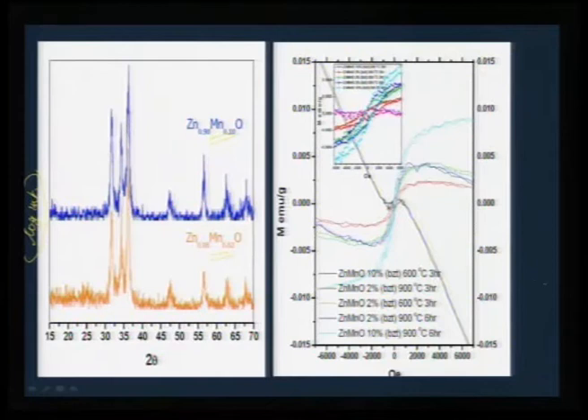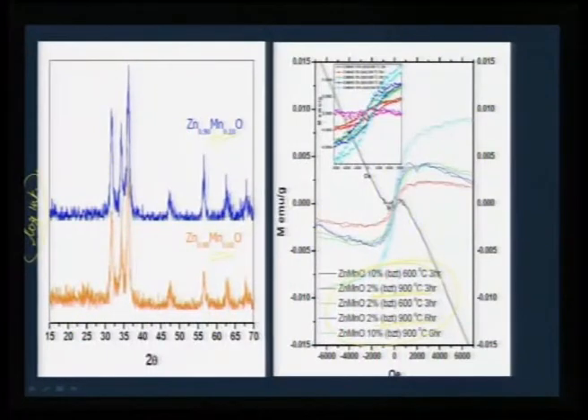Now, the most important feature that I want to draw your attention to is this magnetization versus field plot. And for the first time, we are seeing any sample that is heated above 600 degrees, say at 900 degrees C, showing a very strong ferromagnetic signal.